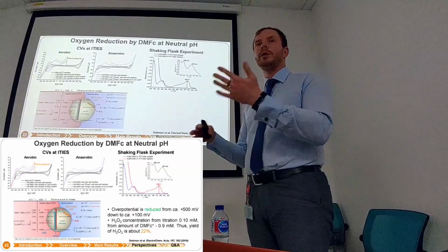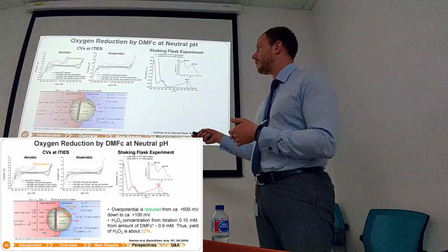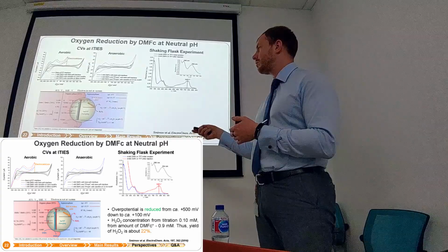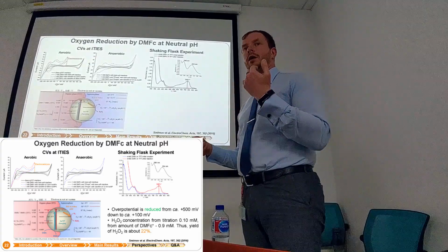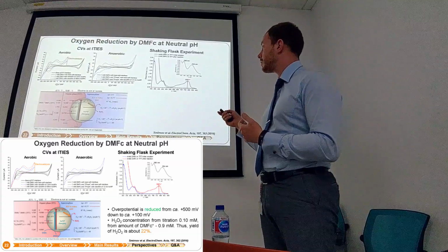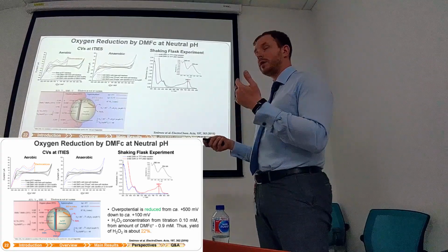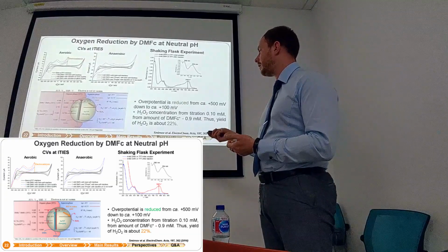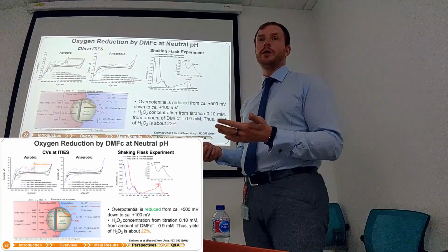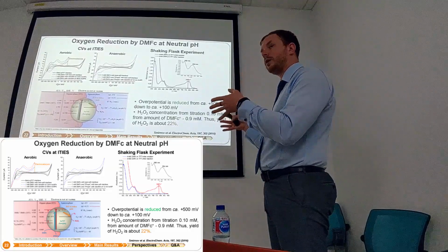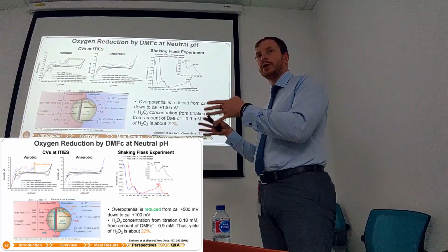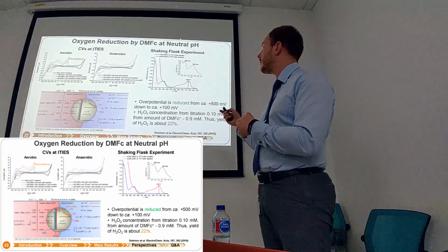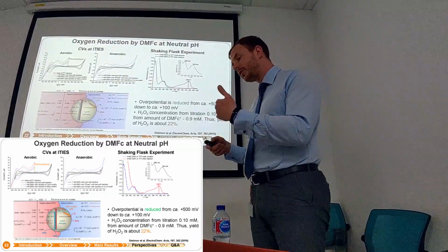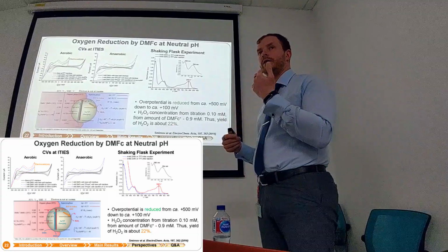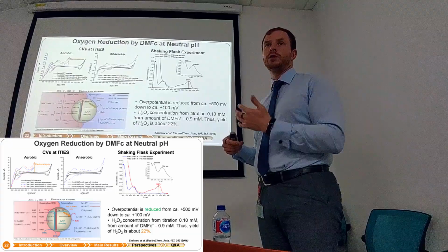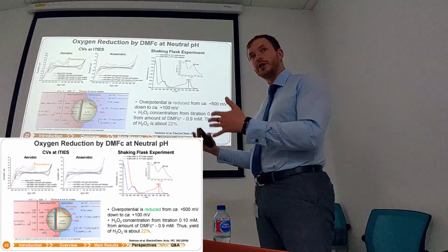And again, the idea behind it: we're charging our nanoparticles from somewhere here up to here. We need some kind of overpotential or driving force, a bit more like this, and then from here electrons can go to the aqueous phase and reduce oxygen to peroxide. And the presence of the peroxide was shown in a shaken flask experiment with the well-known iodine method, and the yield of peroxide was about 20%. Not much, but we showed that nanoparticles really can work as catalytic particles in unusual conditions for them, because at natural pH, catalysis of oxygen reduction on gold especially is almost not possible. But we showed that if we can molecularly charge and discharge, then it's possible.